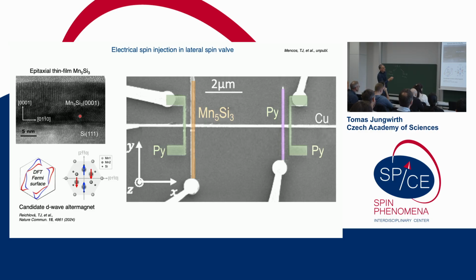So this is the device. The one we're particularly interested in is this one with the compensated magnetic manganese-5 silicon-3 injection electrode. But as you see, our colleagues fabricated a control device, a reference device, in which not only the detection electrode, which is ordinary permalloy, nickel iron, but also the injection electrode is ferromagnetic, so that we can confirm that everything is fine in terms of electrical and spin detection behavior of such a device.